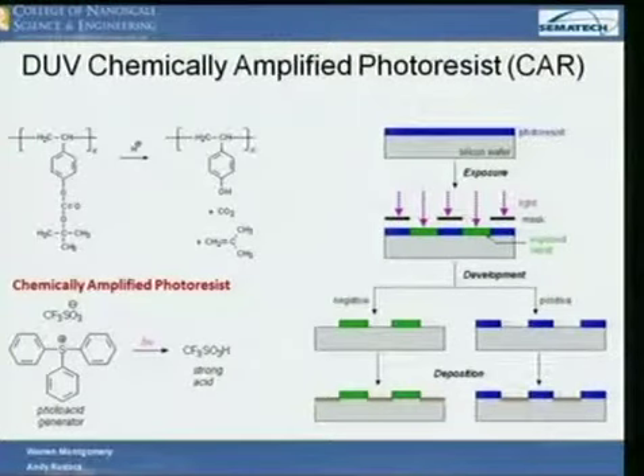What's interesting about this material, and I talked about it a little bit, is that when you develop this in KOH, for example, we don't use KOH for this, we use tetramethylammonium hydroxide, but base developer, it only attacks here. So the area that didn't get exposed doesn't get touched. Now, if you take this film and you develop it in xylene, which is an organic solvent, or the solvent that the photoresist was made in, PGMEA, for example, it would dissolve this, but it won't touch this, which is polyhydroxystyrene. It's not soluble in it. So now you can reverse the tone with the same resist system. This can be both a negative and a positive resist, depending on which developer you use.